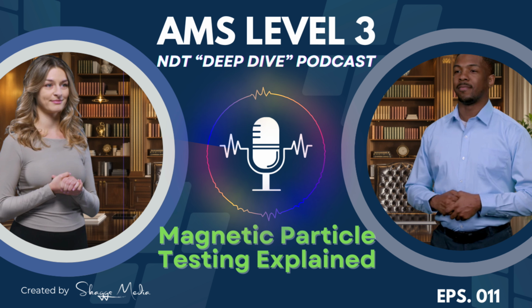Okay. And that leads us nicely into the sort of hybrid option, half-wave rectified current, or HWDC. That seems like the most versatile choice, especially for field work. HWDC is extremely effective, yeah, particularly when you pair it with dry magnetic particles. It's really good at detecting both surface and subsurface flaws. And the reason is the rectifier doesn't produce smooth DC. It creates these pulses of current.